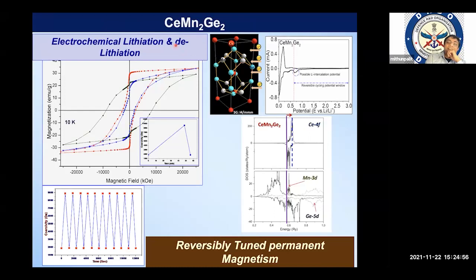So this is a material, an intermetallic, cerium manganese 2 germanium 2. And in this material, you can see that this blue curve, basically prior to insertion of lithium ion, has coercivity very less, around 2000 Oersted.